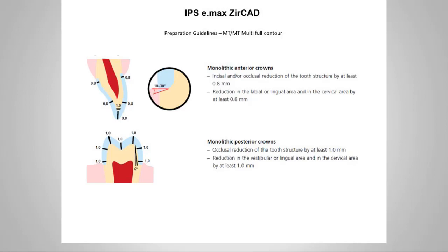For the monolithic anteriors, the incisal and occlusal reduction of the tooth structure should be at least 0.8 of a millimeter. Reduction on the labial and lingual in the cervical area should also be at least 0.8. So if you're using the MT or the multi for full contour, 0.8 of a millimeter is really all you need. You see in the little circle in the middle the type of margin you need. It's basically a chamfer margin. For the monolithic posteriors, you basically need a millimeter. If you can remember a millimeter, then you're going to be fine.